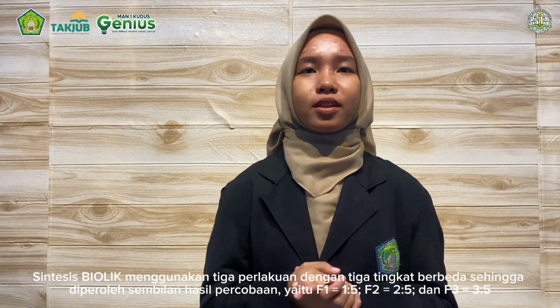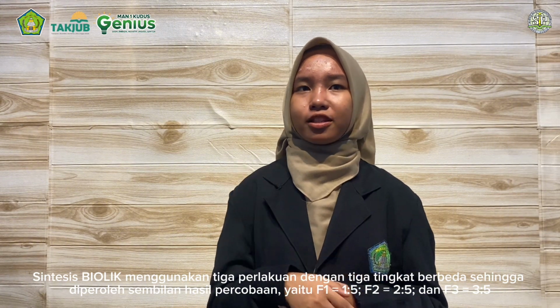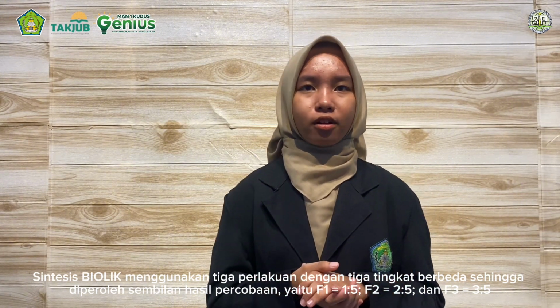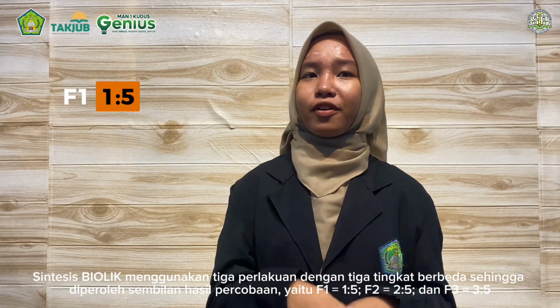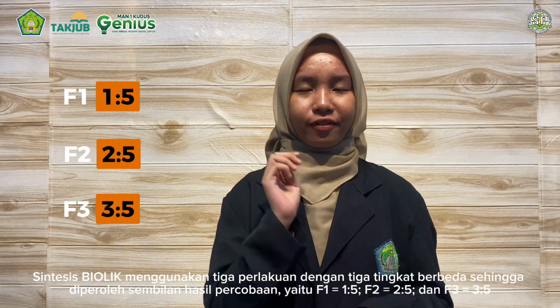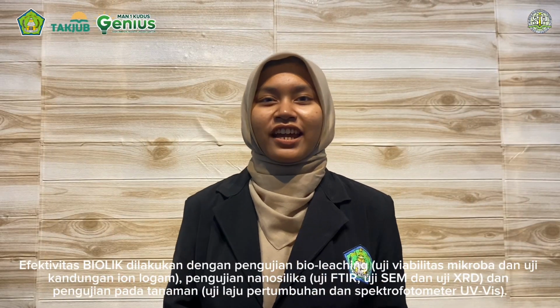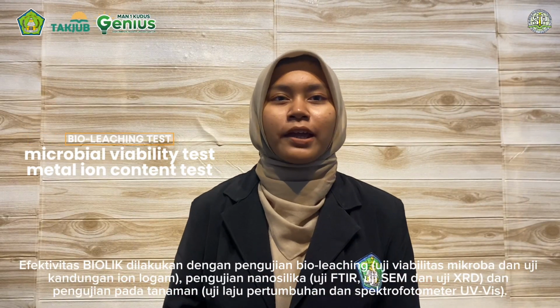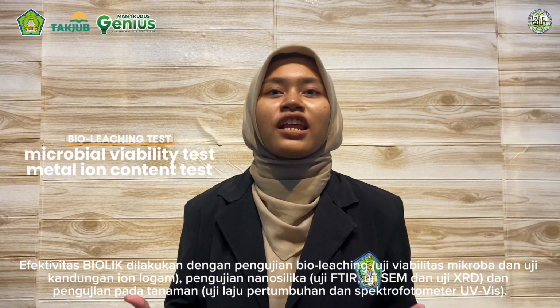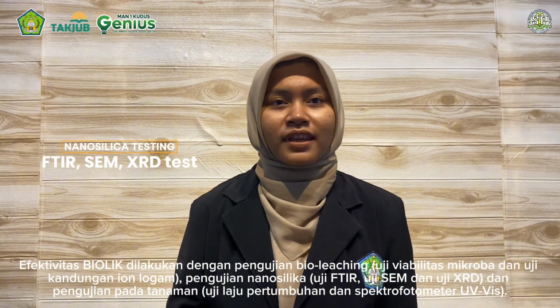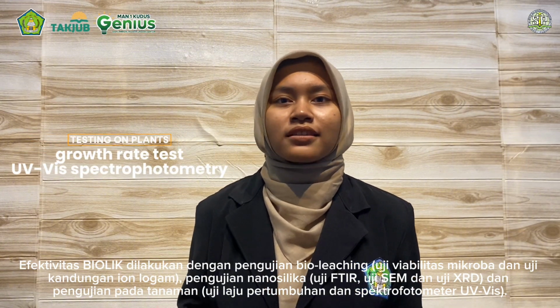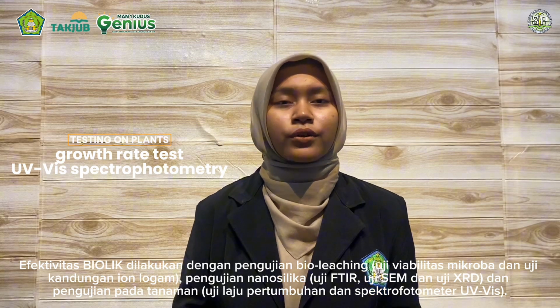Based on the results of the research that has been carried out, the following conclusions can be drawn. First, using three treatments with different levels, nine experimental results were obtained, namely F1 1:5, F2 2:5, and F3 3:5. The effectiveness of BIOLIK is carried out by bio-leaching testing, microbial viability test, and metal ion content test, nanosilica testing, FTIR test, SEM test, and XRD test, and testing on plants, growth rate test, and UV spectrophotometry.